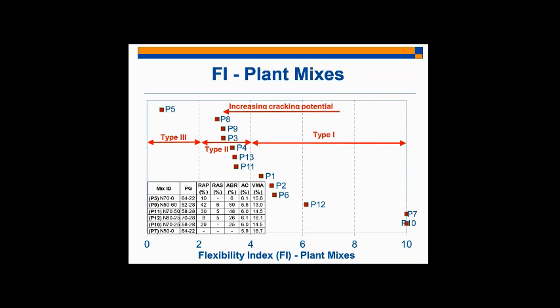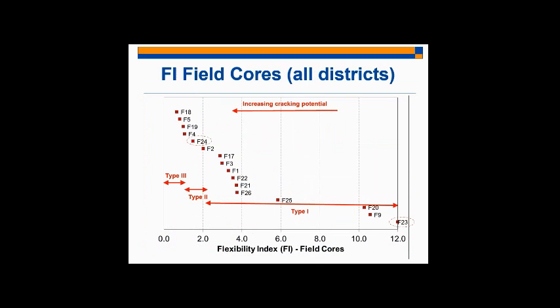So then we looked at our field cores. I mentioned that we had a bunch of field cores from all of the IDOT districts. And we did the same exercise, basically. We plotted them. X-axis is flexibility index. And what you can see here is, again, as you move towards the left of the curve, you have increasing cracking potential.